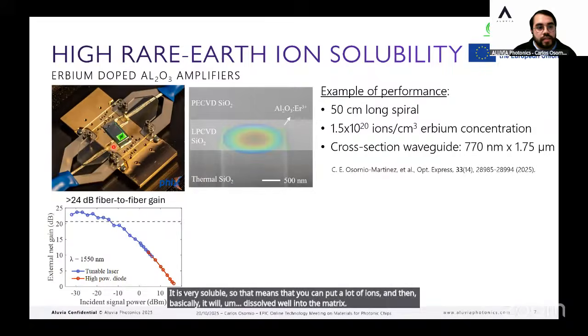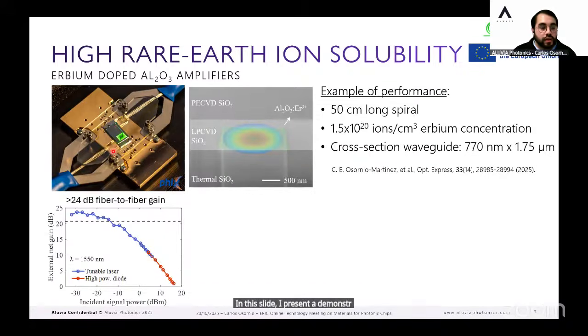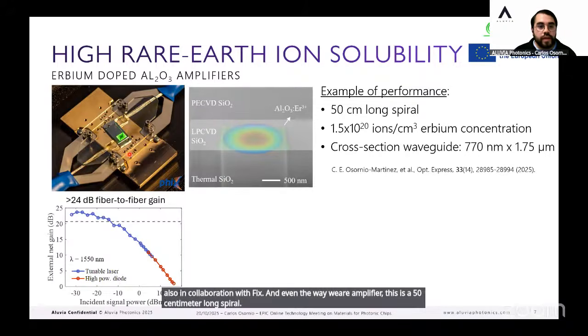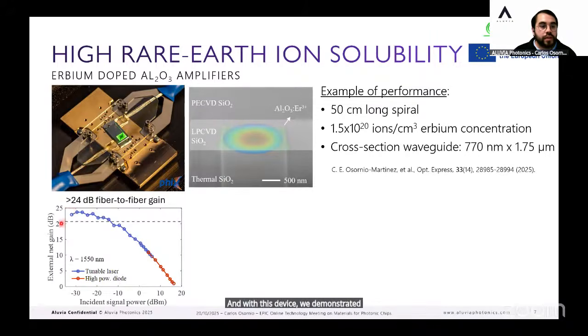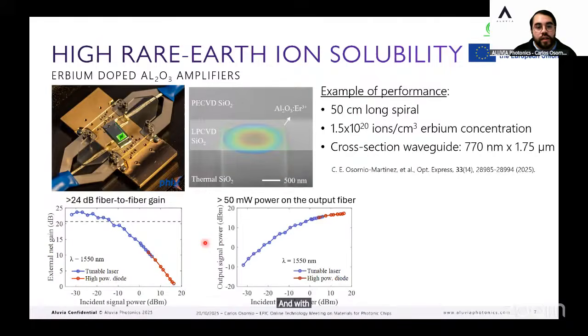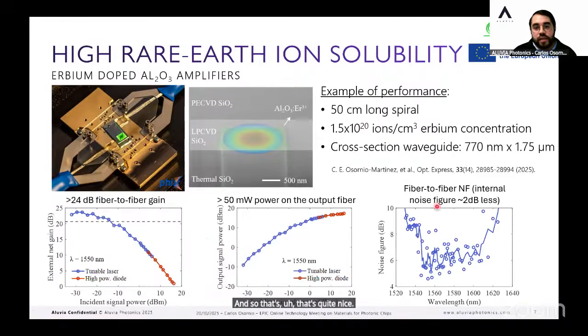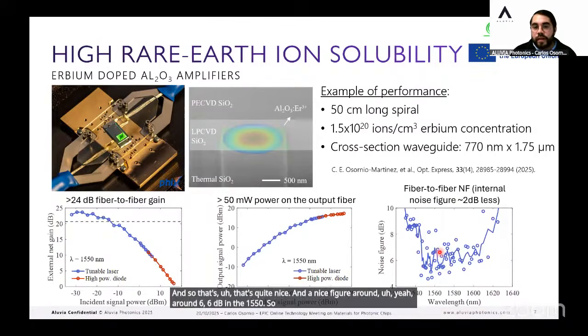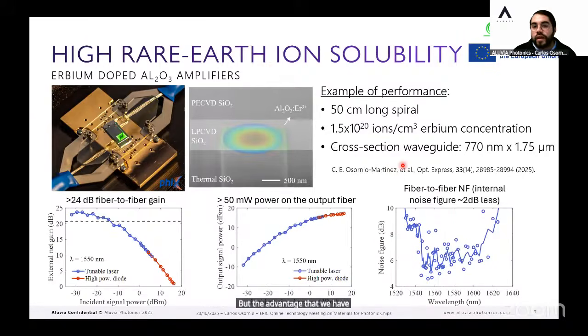In this slide, I present a demonstrator that we made in collaboration with PICs, an erbium doped waveguide amplifier. This is a 50 centimeter long spiral. With this device, we demonstrated almost 25 dB fiber to fiber gain in the small signal, with an output power at the fiber of above 50 milliwatts. That's quite nice. And a noise figure of around 6 dB at 1550. So these specs are comparable to the erbium doped fiber amplifier, but the advantage we have here is reduced size and reduced cost as well.